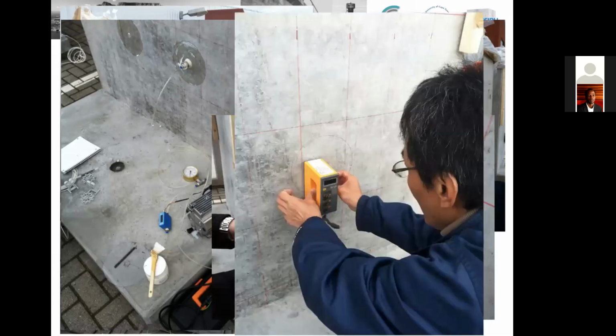Those measurements that are taken in situ normally rely on using moisture measurements of the concrete as a calibration for what you have measured. We don't do that in South Africa because we take samples from the structure and test it under specified, controlled conditions in the laboratory. So we don't have to take account of the moisture content, which is one of the problems of most of the in situ based methods, that you always have to interpret your penetrability test methods with the prevailing moisture condition in the concrete. So if you measure these values in different seasons, you would measure different values. So you have to interpret the concrete quality accordingly.